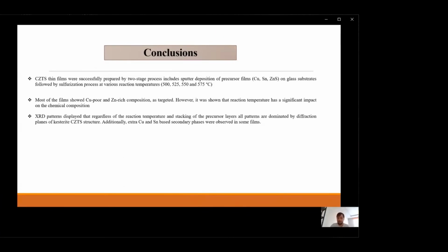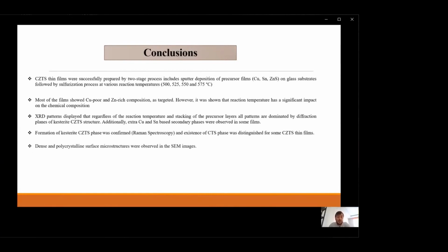XRD patterns displayed the diffraction planes of the CZTS regardless of the stacking order and sulfurization temperature, and some additional copper and tin-based secondary phases were observed in some films. Formation of the kesterite CZTS phase was confirmed by Raman spectroscopy, and the existence of the CTS phase was also distinguished for some CZTS films. Dense and polycrystalline surface microstructure was observed in the SEM images.